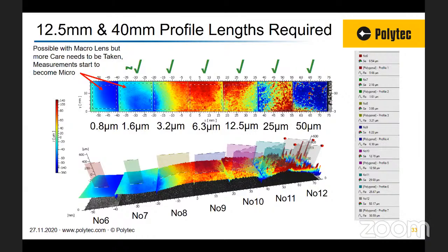The image on the bottom, you can see the profile lengths. And interestingly, manufacturers produce these roughness artifacts. If you're trying to measure them to ISO and you're doing it with a profile type instrument, you can see that it will be virtually impossible to zigzag your stylus across these surface types. So sometimes you need a tactile approach to getting data and to getting stability of data.